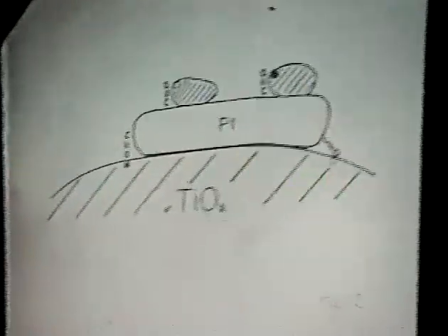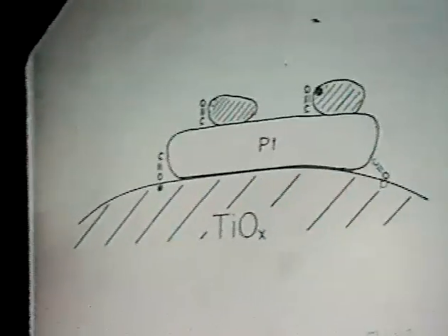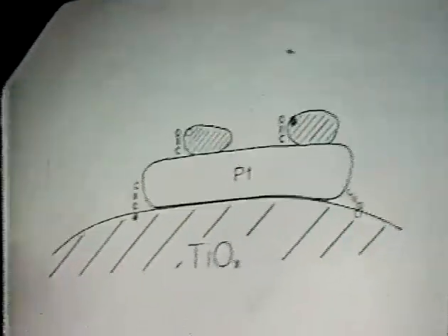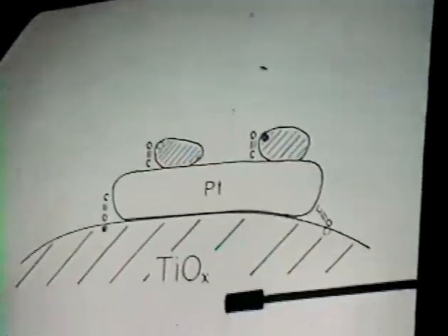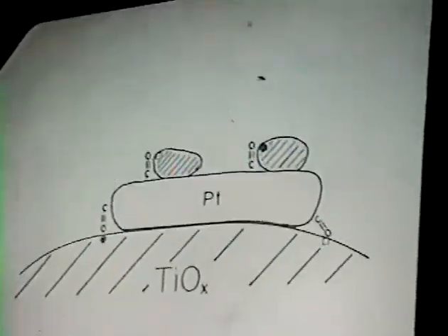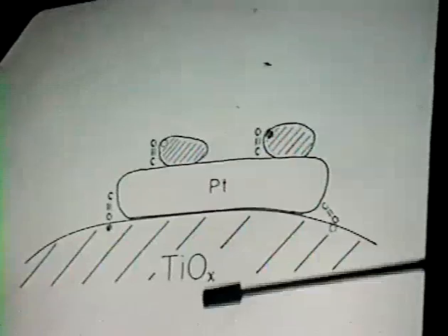Well, these were the results that led us up to this test, and about 5 years ago we had proposed a very simple model to account for the higher rates of hydrogenation of the CO molecule, just by invoking that if we put platinum and titanium, TiOx, when it's reduced at higher temperatures, it can become non-stoichiometric.